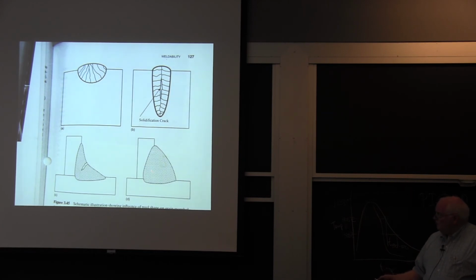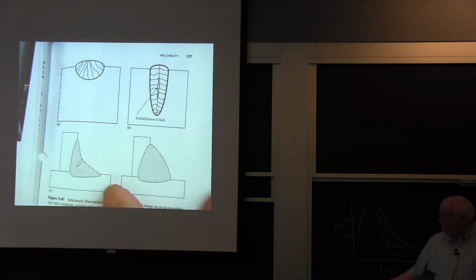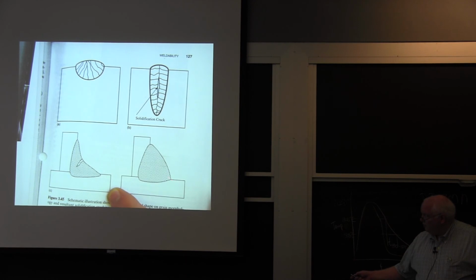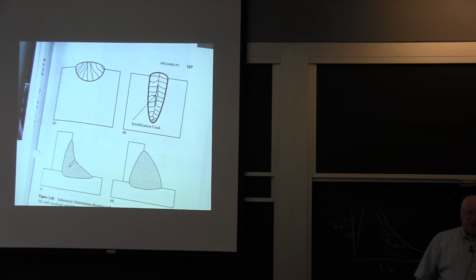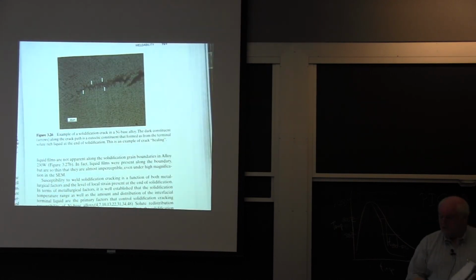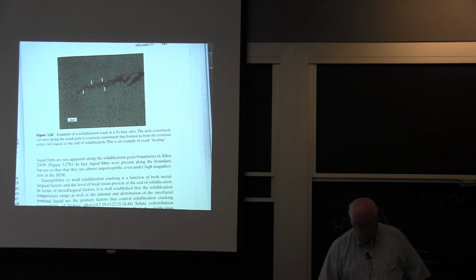Here's a fillet weld. This is good because you have the columnar solidification grains growing from the edge out and pushing the liquid out here. If you have something like this, you actually will collect it in the seam right here, and so the weld profile makes a difference. Okay, not just for fatigue. This would be a good profile for fatigue. This is a worse profile for fatigue, a higher stress concentration at that corner than this corner, but this is lousy for solidification cracking. You can get solidification cracking in steels, but you got to really try. Okay, store a lot of phosphorus in there, and you can crack a steel.